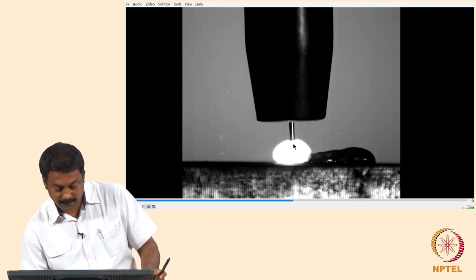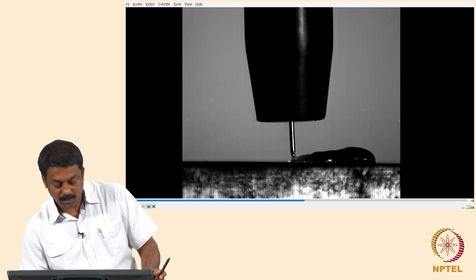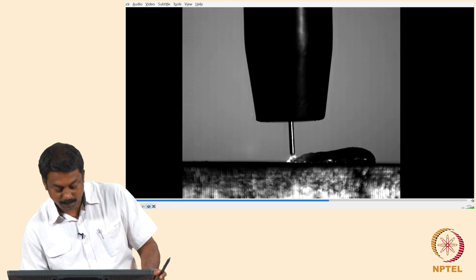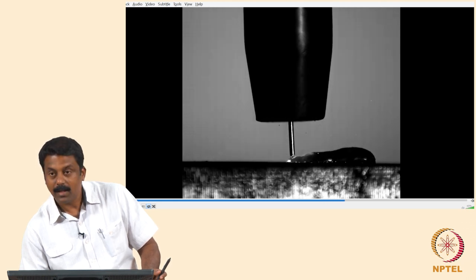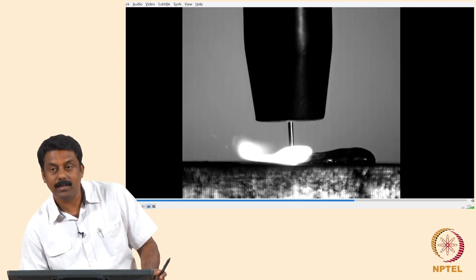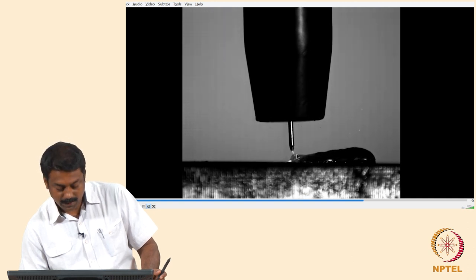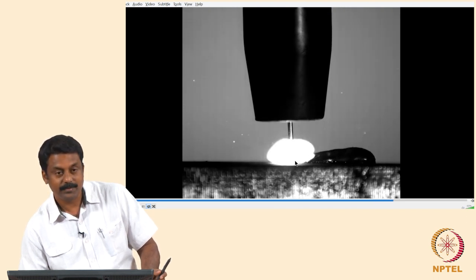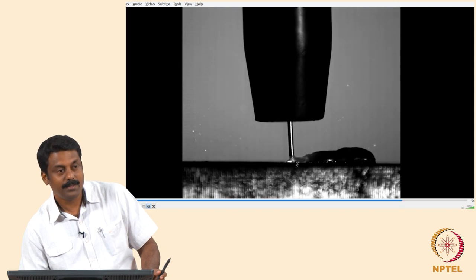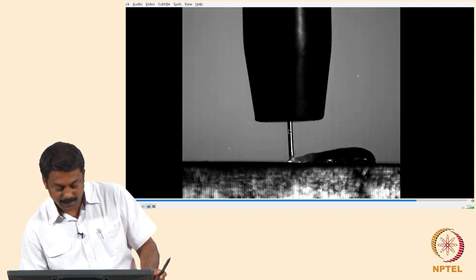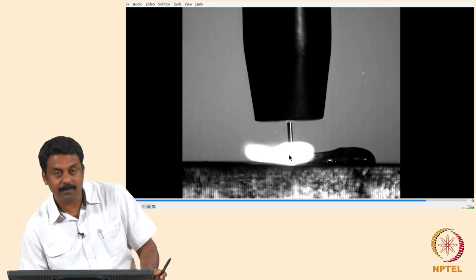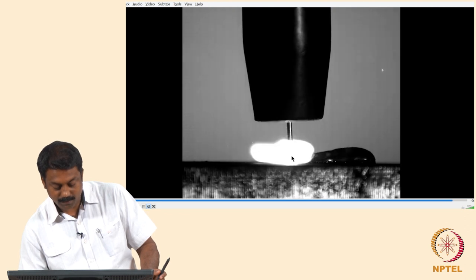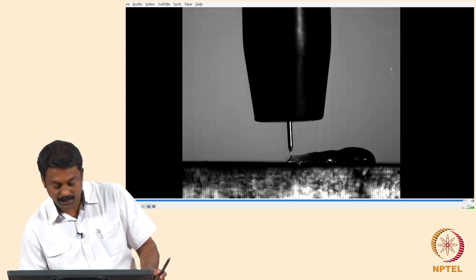To achieve this process, extreme synchronization is needed. We have to control the wire feed rate, control the arcing period, control the moment at which the short-circuiting happens, measure the moment it happens, and then play around the waveforms so that the droplet is transferred without any explosion. The actions involved are: the arc, the back-and-front movement of the electrode, the short-circuiting event, and then the metal transfer by the collapse of the droplet to the weld pool.